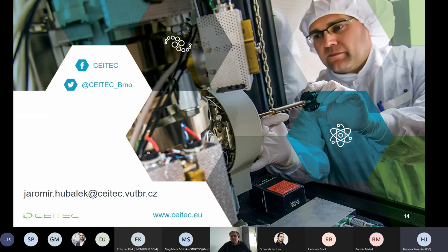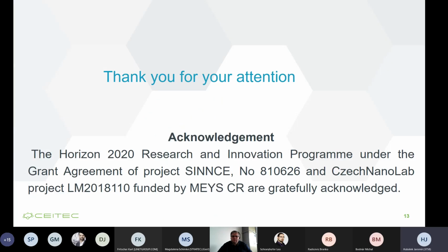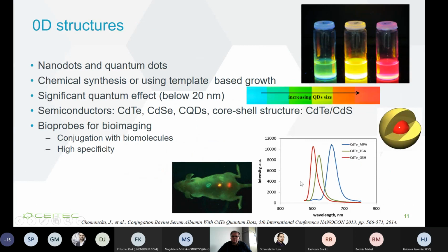But with encapsulation, for example with GSH, these materials help to eliminate the cytotoxicity of these particles. They were coating the particles with proteins to make them compatible. Especially, this modification or functionalization also allows modification with antibodies and antigens for detection. So it is another advantage of this covering or encapsulation.